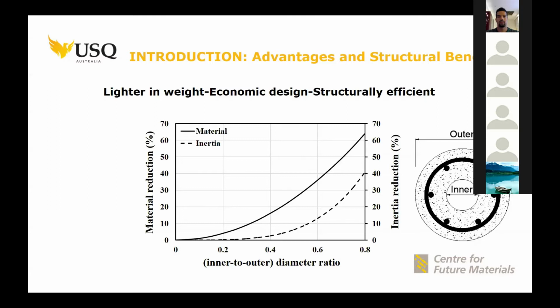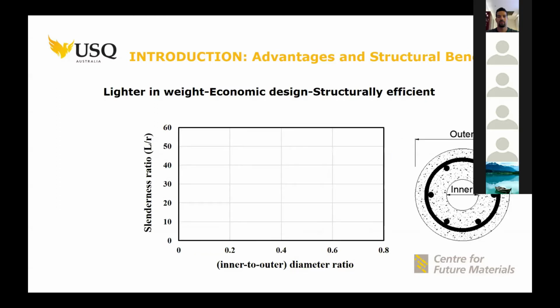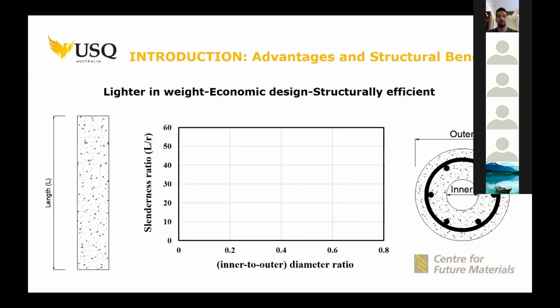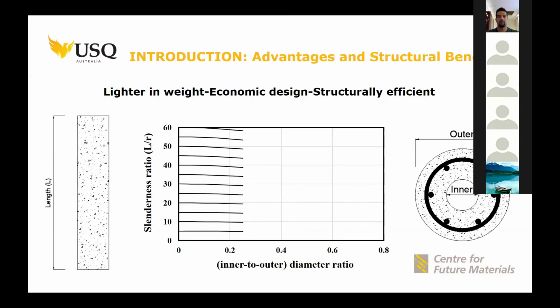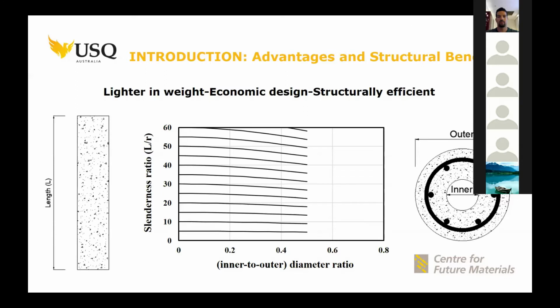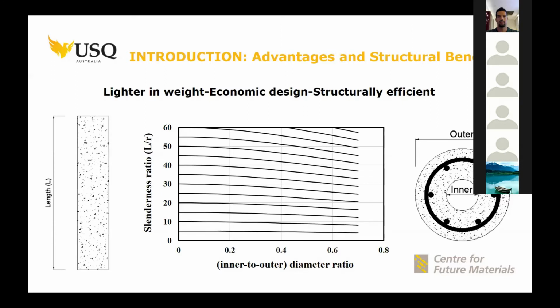After that, I looked at the stability of the hollow concrete cross sections, and I found that with the slenderness ratio aspect, if you increase the inner to outer diameter ratio, you are reducing the limit of slenderness ratio. And all of these aspects got me more convinced about that application and to investigate it more.